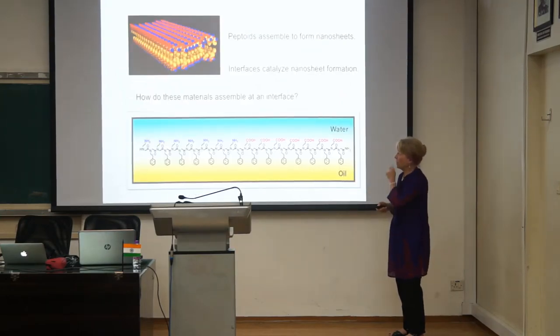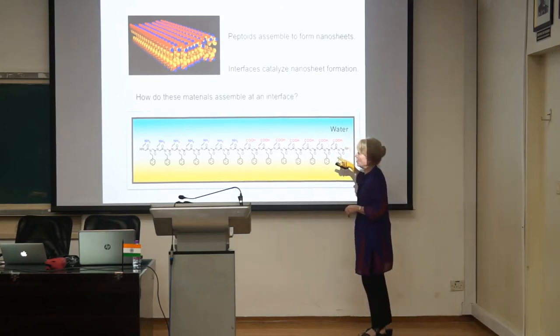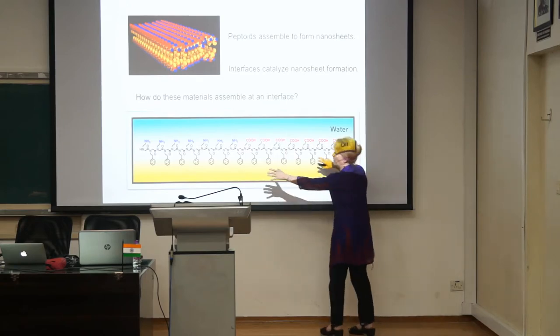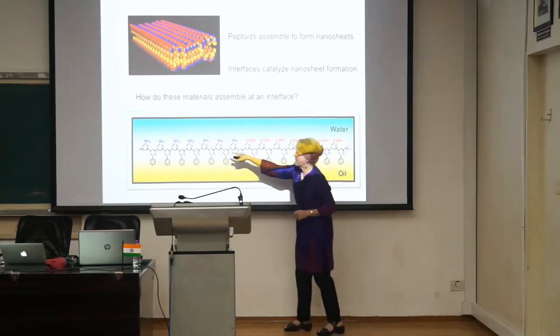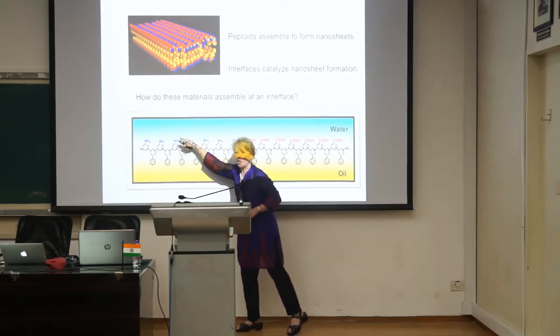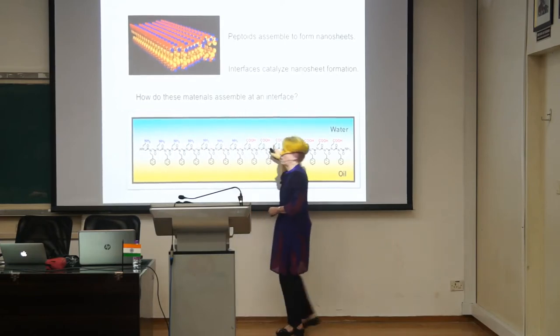And then just building on this was to take peptoid sheets and look at how they assemble at the interface too, doing the spectroscopy of the sheets. Peptoids are an interesting possibility for drug delivery systems as well as other materials. They have all these amine groups and then carboxylic acid groups. The question was, why do you get these ordered polymers, peptoids, that form at an interface? What we did was to actually show that these polymers lay down on each other because as the next layer goes down, its amines go here and its carboxylic acids go here, and then it alternates. And we were able to pick up the spectral signature that shows that the CH2 is bonded to the carboxylic acid.